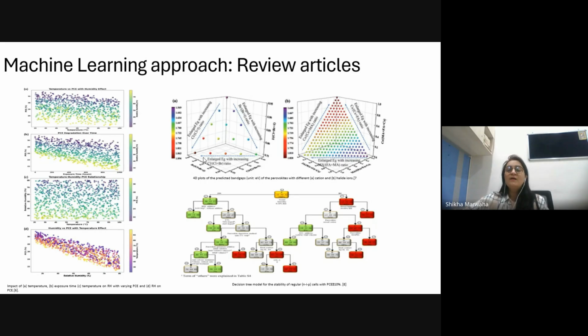So here we have Cl divided by Cl plus Br, then bromine by bromine plus iodine ratio, and then chlorine by chlorine plus iodine ratio. So this is the trend for the increase or decrease of the band gap based on its cations or halides. And the second is based on methyl ammonium, formamidinium and cesium. So how my cations are behaving and how my anions are behaving, and what are their combinations.